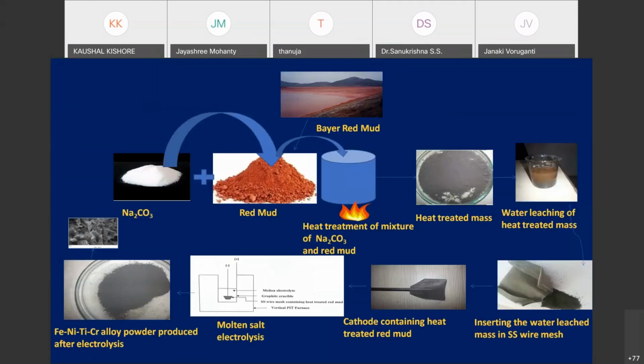So if you see, the whole process consists of a series of procedures. The first one is that the red mud is heat treated with sodium carbonate, and after heat treatment in the graphite crucible, it is taken out, and the material is like this heat treated mass. This heat treated mass is water leached to remove any kind of water soluble materials. Then after drying the leached mass, we have taken this material into a stainless steel basket type structure, and we have put it here in the basket type material.